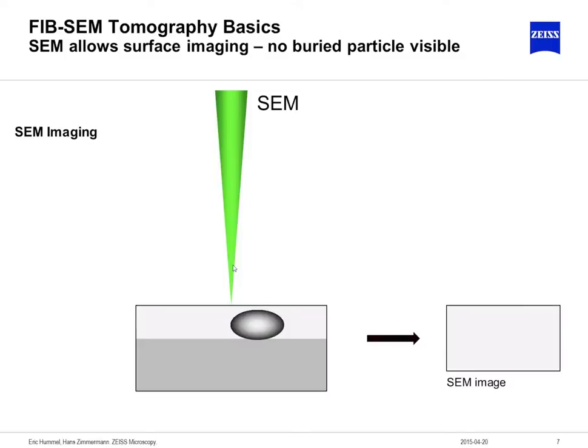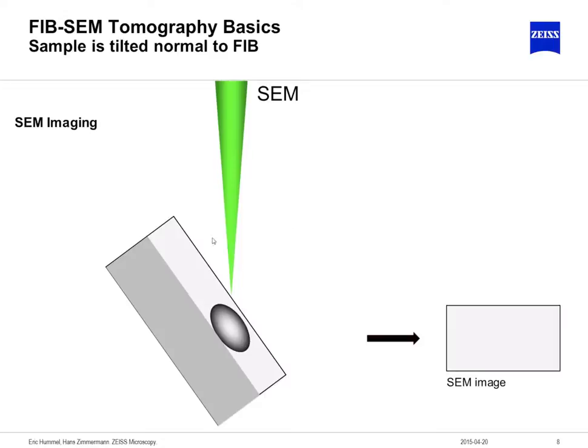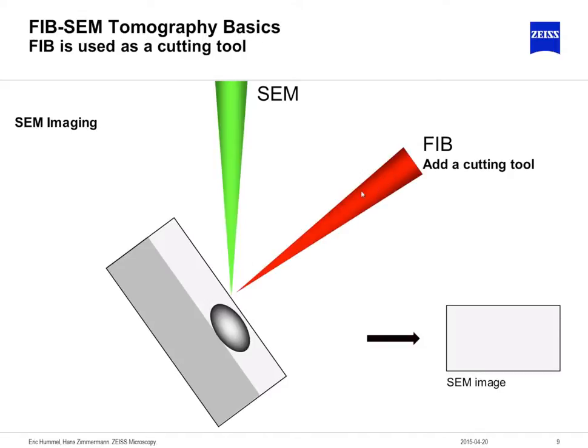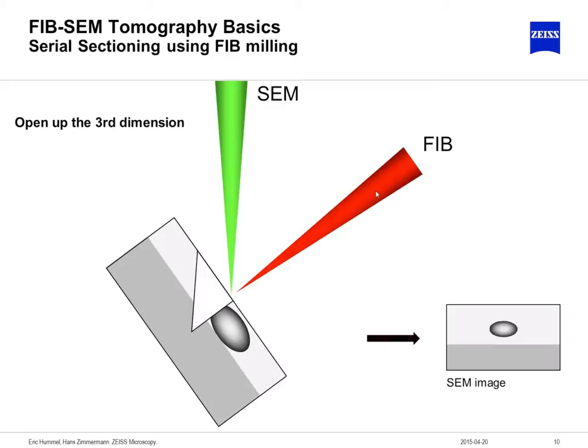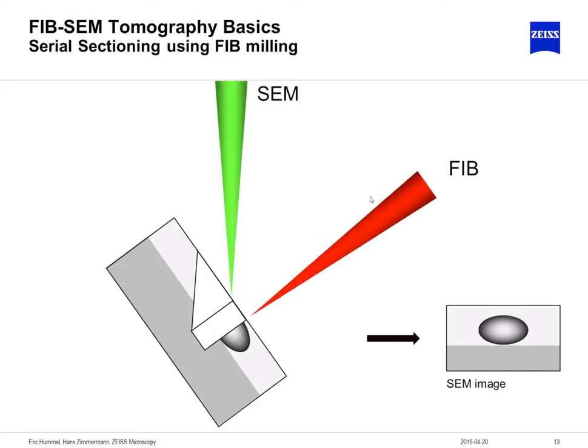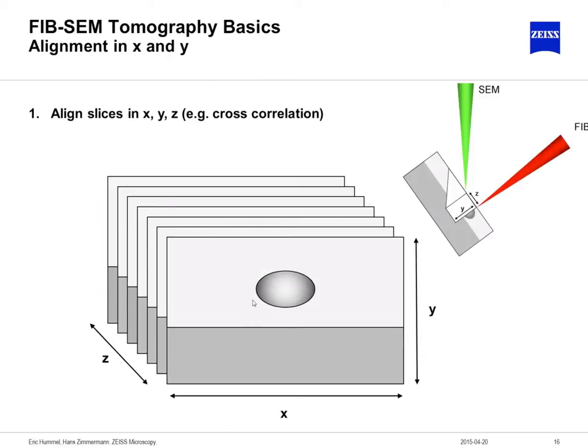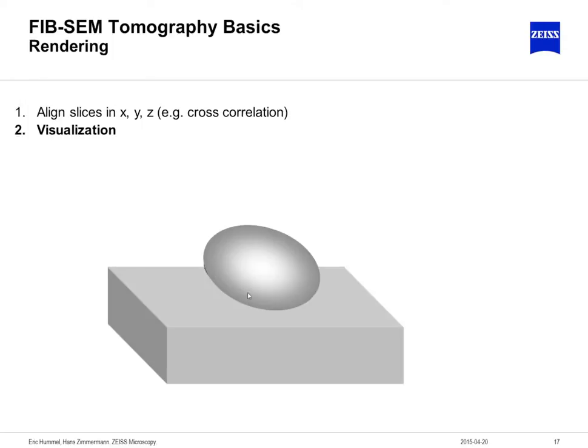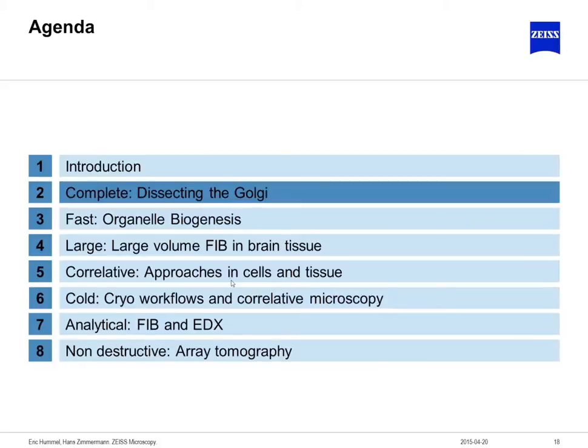I will focus here on a specific topic: focused ion beam tomography. Typical SEM imaging is based on constant scanning of a block surface, providing information about the surface of the sample. With focused ion beam, you have a second column included which uses gallium ions to section very thin sections of your block surface. Every time one section is done, the SEM scans the surface of the image, and you end up with a 3D tomogram of the acquired volume. In the second step, we start the visualization in 3D or as a typical tomogram, and we get a full sample of the cells of interest.